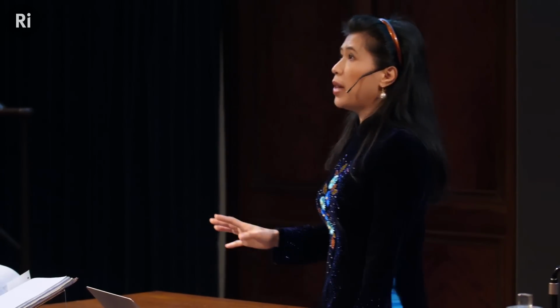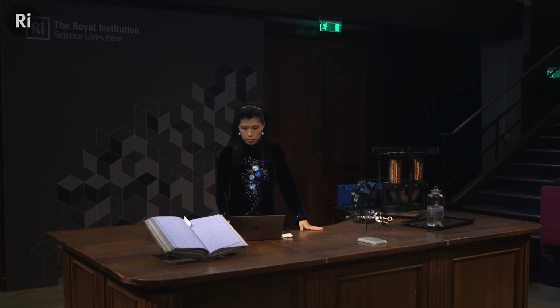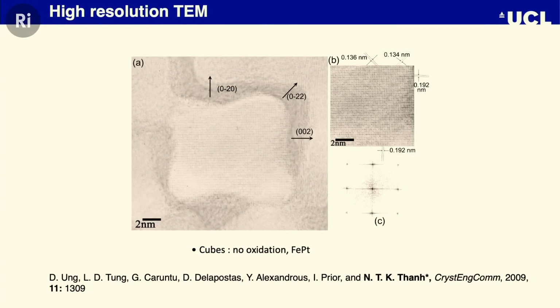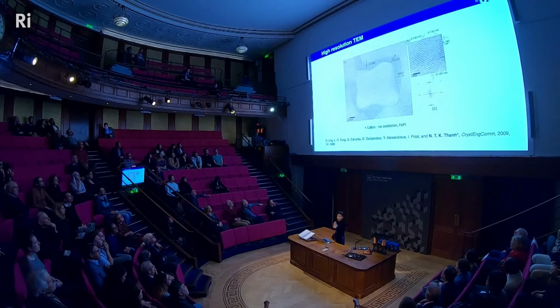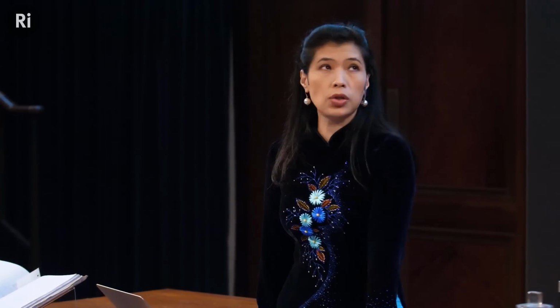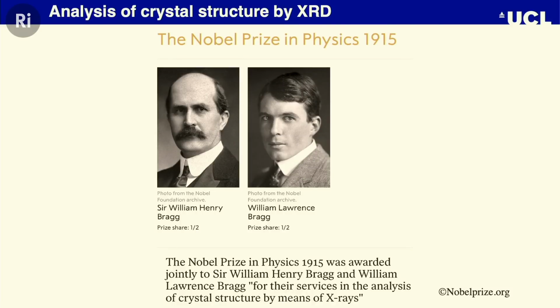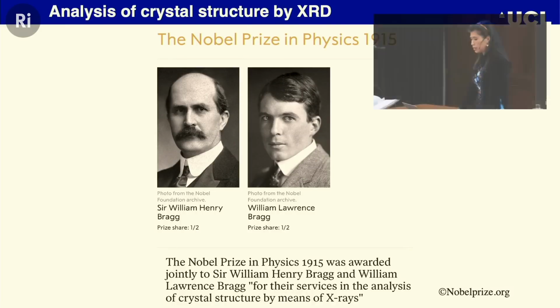Whatever we make, we need to characterize it so that we understand why it forms the way it does. One of the techniques we use is high resolution transmission electron microscopy. You can see the different crystal lattices, and from the known crystal lattice you can index whether they are iron oxide or iron platinum, okay? And then routinely, we use many characterization techniques, but one of them is that we need to analyze the structure by X-ray diffraction.